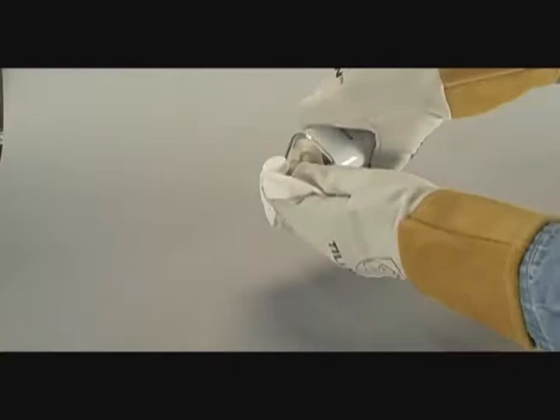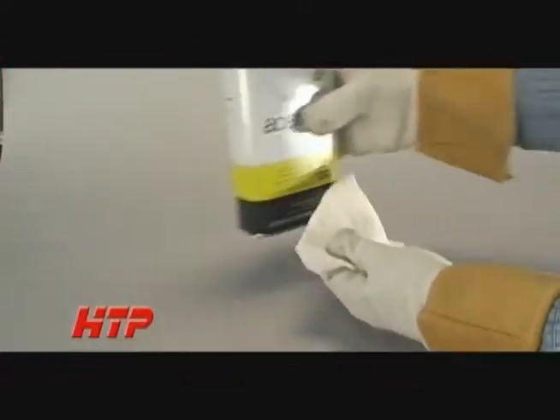It is important to work with clean material. Acetone would be our first choice for cleaning the metal. If acetone is not available, lacquer thinner can be used, but it leaves a slight residue. Do not use brake clean, as the arc reacts with this cleaner to produce dangerous gas, which is very harmful and will make you sick.